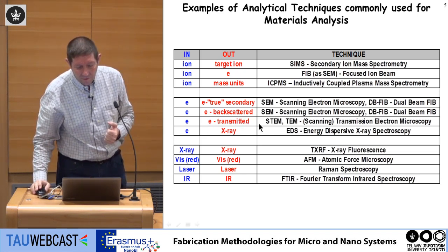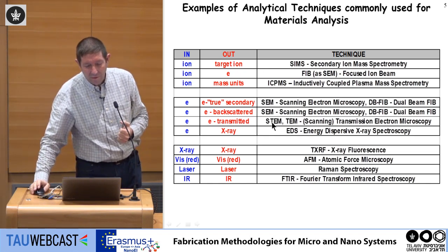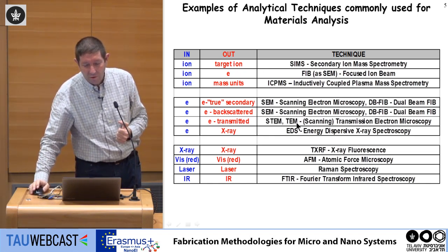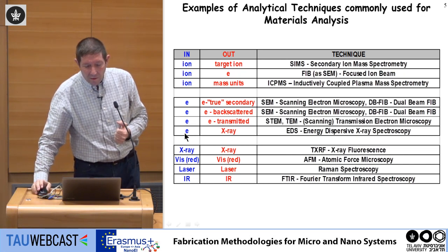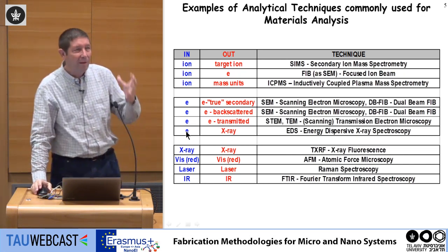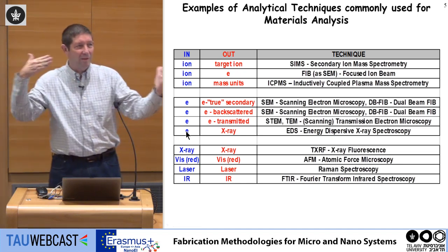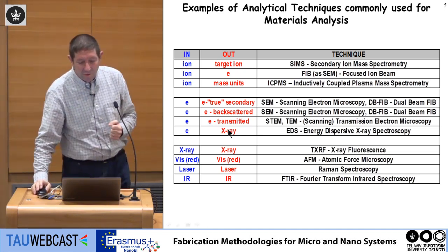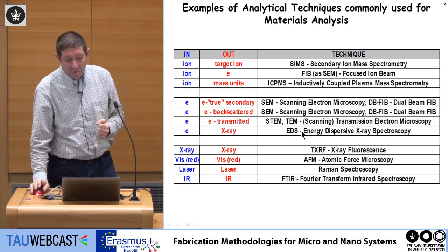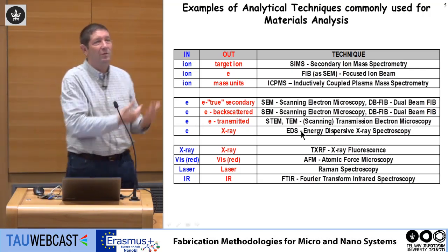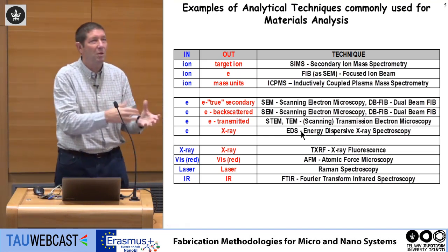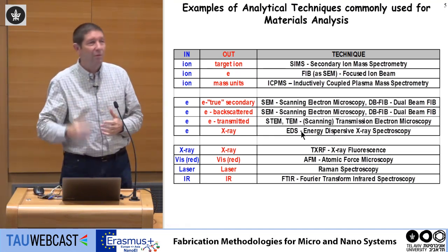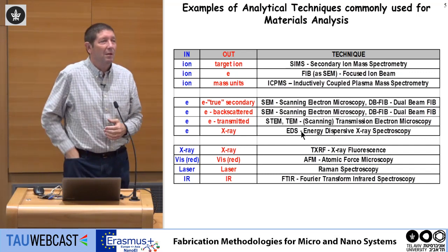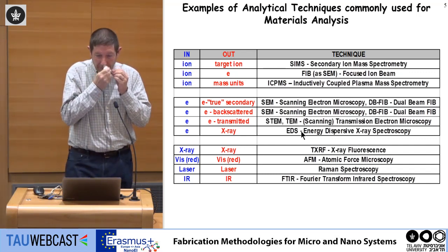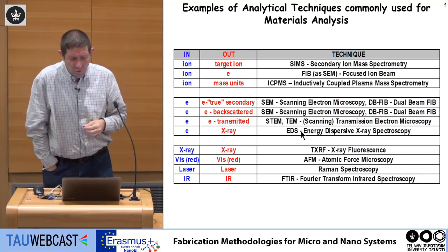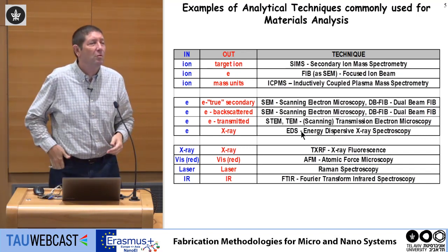I can use transmittance, and this is scanning transmission electron microscopy or transmission electron microscopy. When I illuminate with electrons, illuminate is metaphorically, when I take electrons and shoot them on the surface, I can generate X-ray. And the X-ray is proportional to the mass of the atoms of the target. We know that heavier atoms emit X-rays in different wavelengths, and the wavelength depends on the mass of the atom. So this is called energy dispersive X-ray spectroscopy, which is very useful to measure composition of samples.